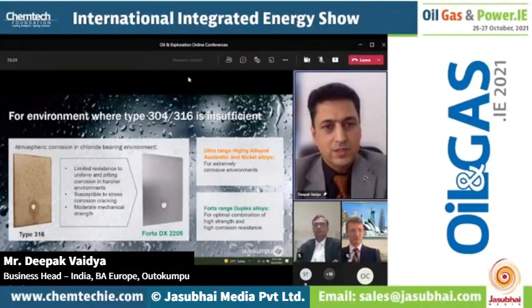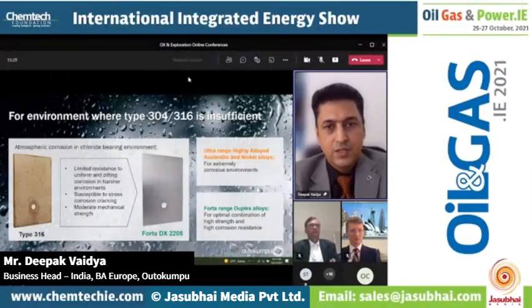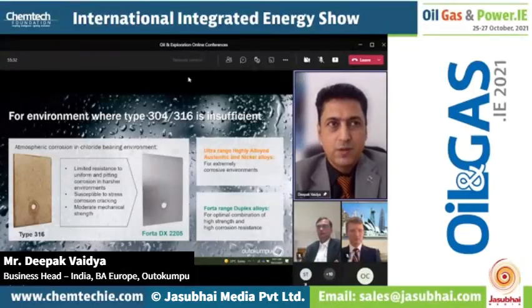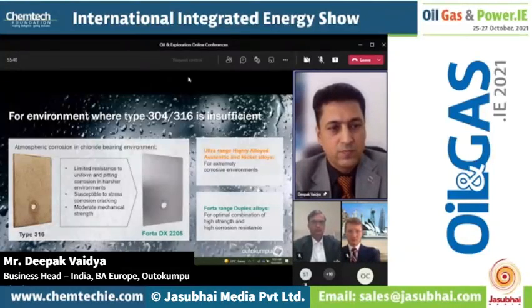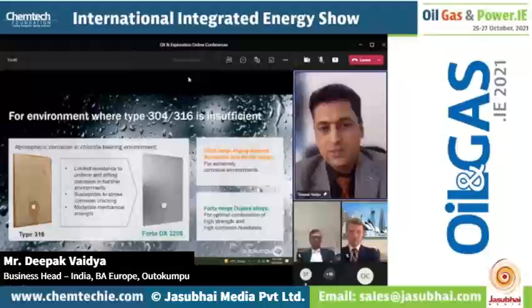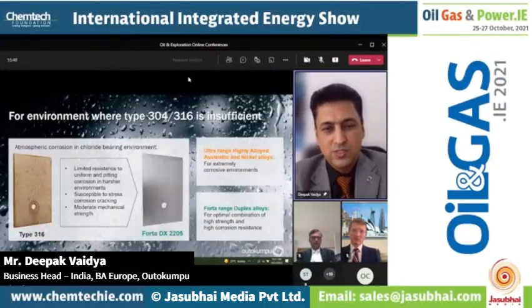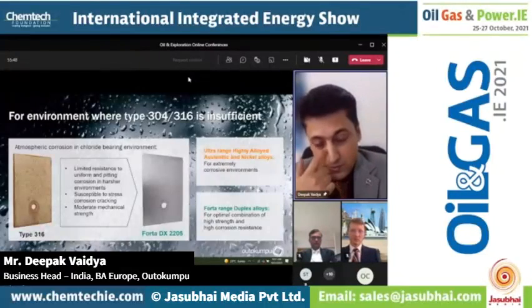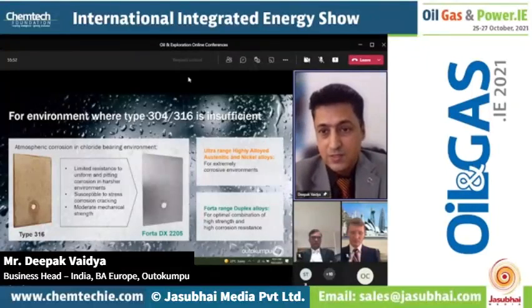So presently, let us focus on oil and gas industry tank farms. Most of the tank farms are near the coastal areas or in higher corrosion-prone areas, and there 304 and 316L are not enough. Many studies have been done on that. On the left side, you see this is a 316L, it has corroded. On the right side, in almost the same service life, you see the surface is very clean.